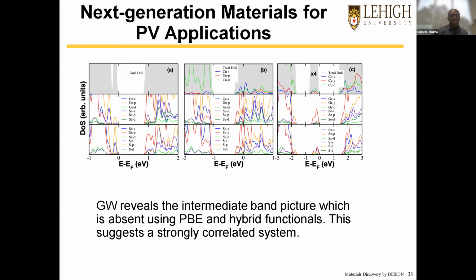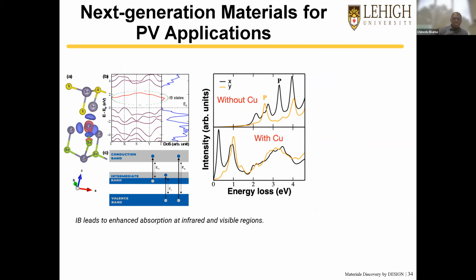As you can see, the intermediate band gap is only revealed when we turn on many-body interaction. So what we also say here is that this material is driven by many-body interaction, which is a signature of a strongly correlated system. So in our material design, we have achieved an intermediate band system without heavy doping, and that is also strongly correlated naturally, because quantum confinement in 2D structures generally engineers a strong electron interaction.